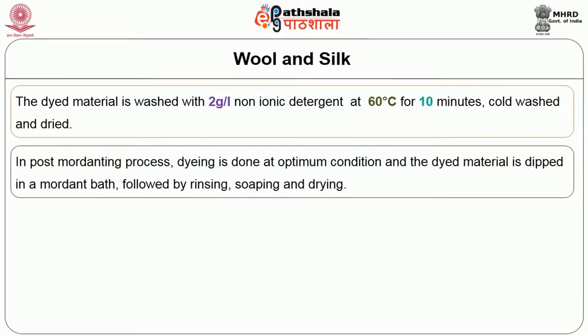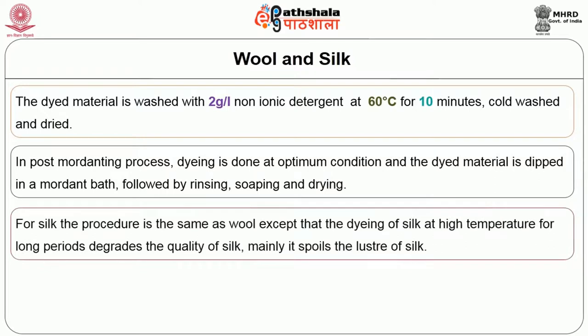In the post-mordanting process, dyeing is done at optimum conditions and the dyed material is dipped in a mordant bath, followed by rinsing, soaping and drying. For silk, the procedure is the same as wool, except that dyeing silk at high temperature for long periods degrades the quality of silk — mainly it spoils the luster of silk. Hence, the material is not heated in the dye bath.